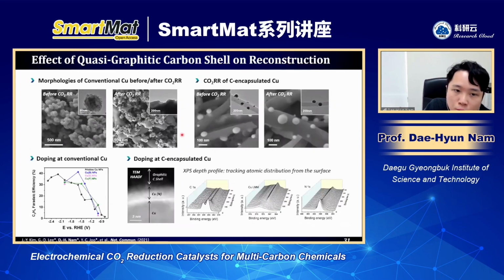And then we compared the structures of the copper before and after, in the case of bare copper and copper with a carbon shell. If you look at this left-hand side one, there is a huge structure change between before and after CO2R in the conventional copper. But in the case of the carbon-encapsulated copper, we can see that the copper structure has been maintained. It means that although there can be some reconstruction, the structure has not been changed severely.